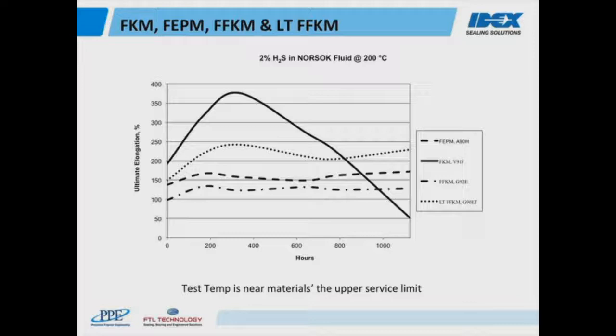As before, the ultimate elongation of the sample in percentage is on the y-axis and the time in hours is on the x-axis. The materials tested are a peroxide cured FKM Endura V91J, an FEPM Endura A90H, an FFKM Perlast G92E, and a low temperature FFKM Perlast Ice G90LT. This really is a good representation of high quality elastomers used today in critical service.